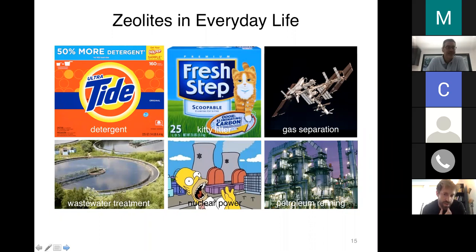And in this case, the zeolites served to soak up radioactive iodine and cesium that were produced during the meltdown. And these harmful species were essentially sequestered inside of the pores of the zeolites. And the workers then took the contaminated zeolite powder and melted it down. And what this did is it trapped these radioactive species inside of the material, which ultimately became glass once it was melted down. In this way, the waste could be disposed safely without worries about the radioactive elements leaching back out.